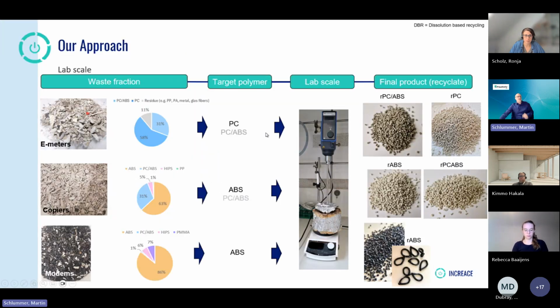So what did we find out in the INCREACE project? We looked, for sure again in the lab scale, at many different fractions we got from mechanical pre-treatment. We see here plastic fractions from E-meters, copiers, and modems. And we looked with specific solvents into the shares of PC, ABS, and others. You see that the shares of PC plus PC ABS are quite high in all these fractions. And if we then go into the pure dissolution process, we achieved getting back a pure recycled PC, and as a co-product we also got a PC ABS.